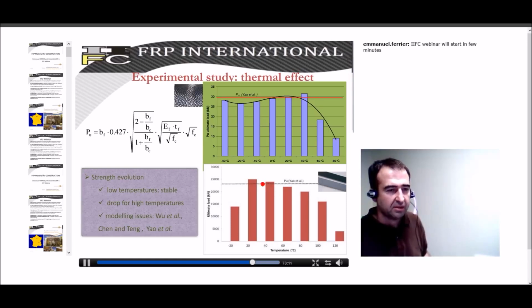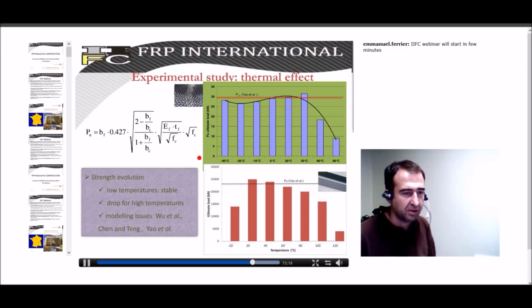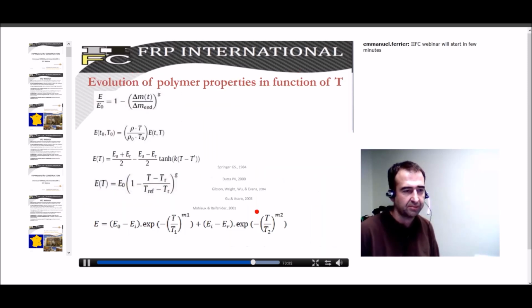And the same is true for laminate. Laminate is good for 20 Celsius degrees, and the model is calibrated for this value, but for low temperature it is not good, and for high temperature it is not good either. So this is an important problem because we can have low temperature and load for bridges and other kinds of applications. So we went back to modeling and tried to see what existed in the literature.